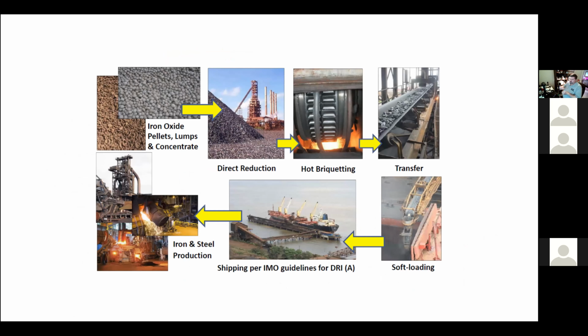So I promised to show you guys a little bit about direct reduction. So direct reduction, there are two main processes that dominate the market right now. And they're both shaft furnace technologies. So they take iron oxide pellets. Some operations use lump, but the problem with lump ore is that it tends to be fragile and you generate a lot of dust, which then gets blown out of the furnace. So you take a yield loss.